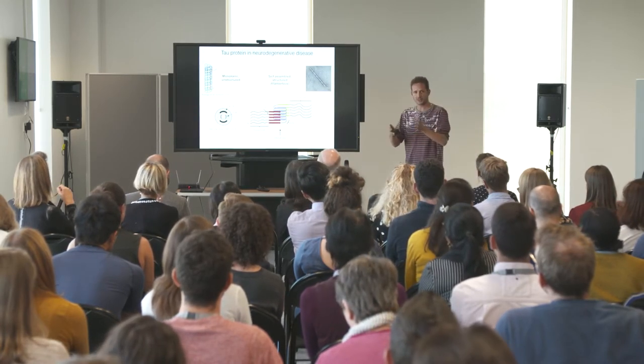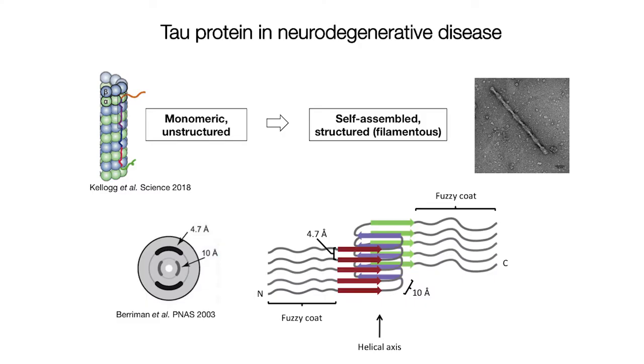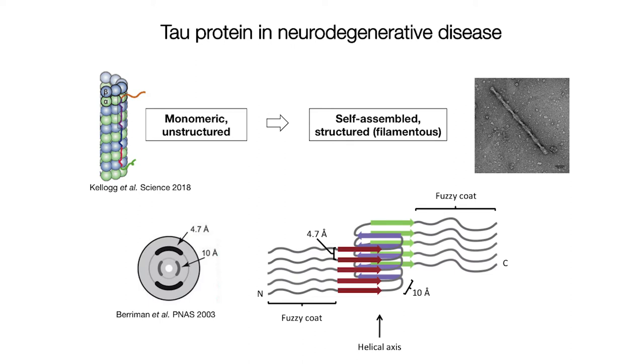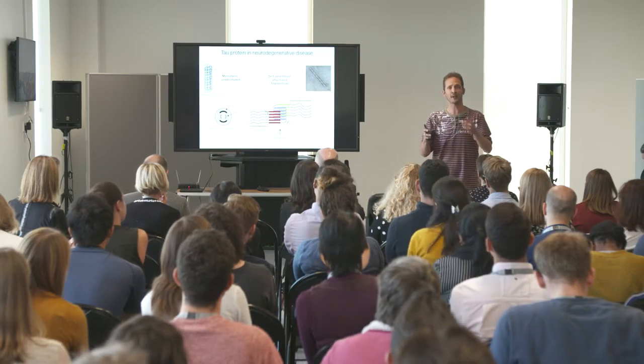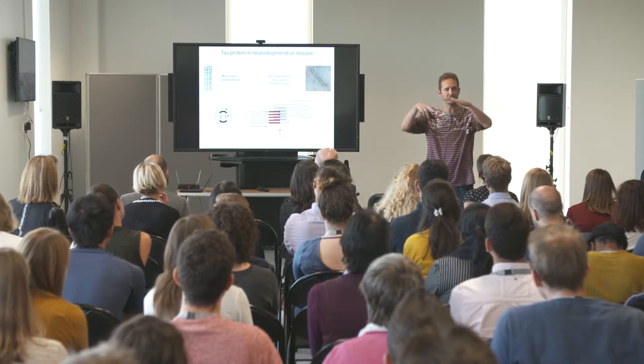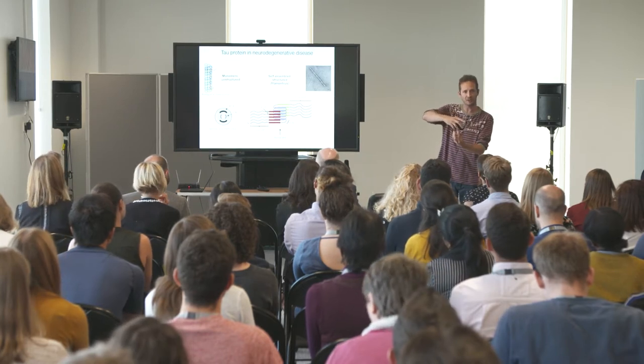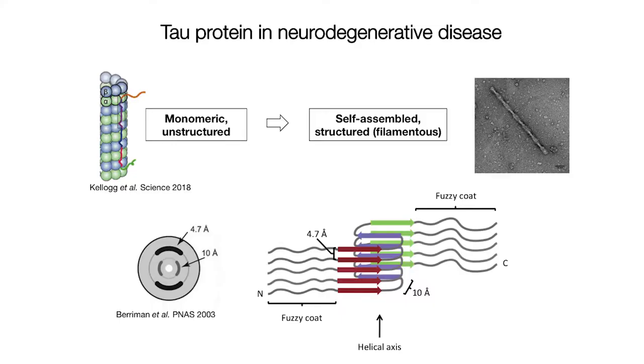Part of what is related to all this is the aggregation of tau through a process called seeded aggregation. If you look at the aggregates of tau in the brains, you can isolate these helical filamentous long arrangements of aggregated protein. If you shine X-rays on them, you get this typical cross-beta pattern, which has features of 4.7 angstroms — half a nanometer — which is the distance between beta strands when you pack proteins on top of each other. These filaments basically form beta sheets along the helical axis, and these pack against each other giving rise to a 10 angstrom packing distance.